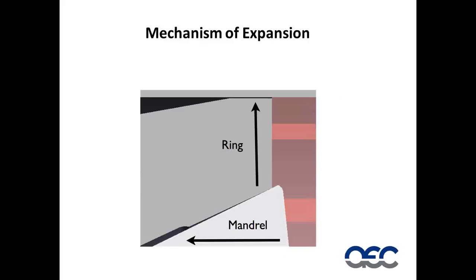Basically, the mechanism is like this. We have a mandrel that's moving somewhere between 20 to 35 thousandths of an inch. We have an angle between 20 to 35 degrees, and our goal is to expand the ring somewhere between 30 to 40 thousandths of an inch on diameter.